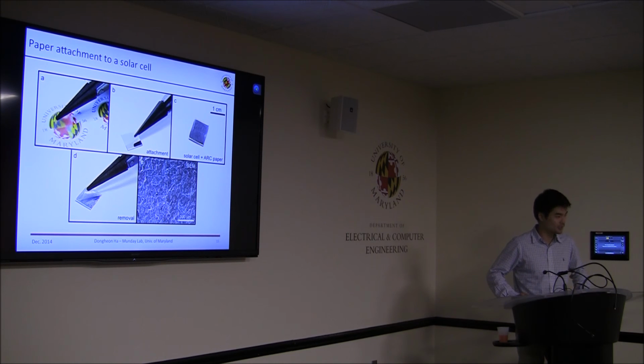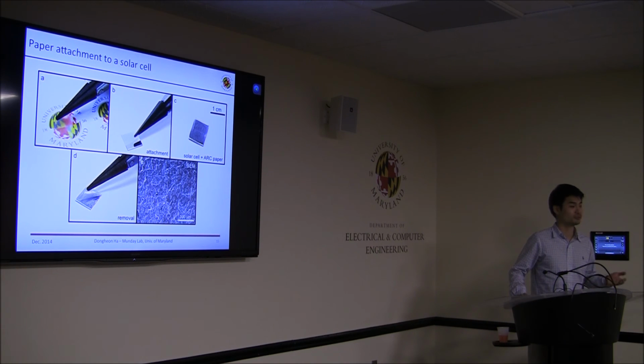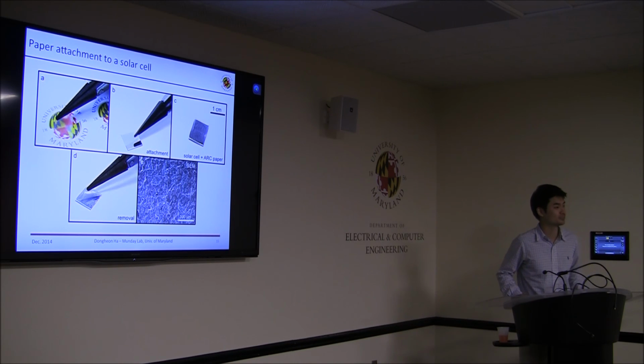That's why I didn't say anything about the phase effect when I was talking about my optical model. I can calculate the estimated reflectivity just based on the change of the refractive index. However, as you pointed out, if the thickness is less than 1 micron, or somewhere comparable to the wavelengths, definitely we need to consider the effect of the phase shift or something like that. So that is true, but for my research, that's not critical.